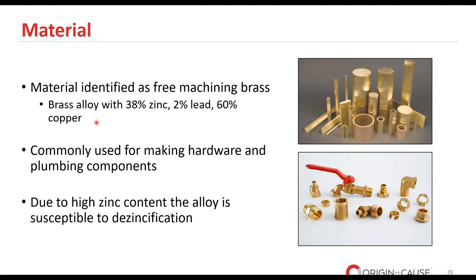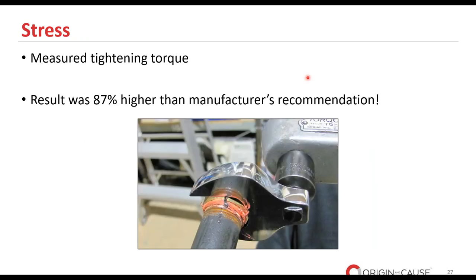Let's talk more about some of the testing that was performed during our investigation. Shifting our focus to mechanical stress aspects, we performed torque measurements on the valve. So torque, in essence, gives us an understanding of how much force was used during tightening. The results were pretty telling. The measured torque surpassed the manufacturer's recommended levels by a staggering 87%. And such a deviation from recommended values can really strain the material and significantly contribute to premature failures.